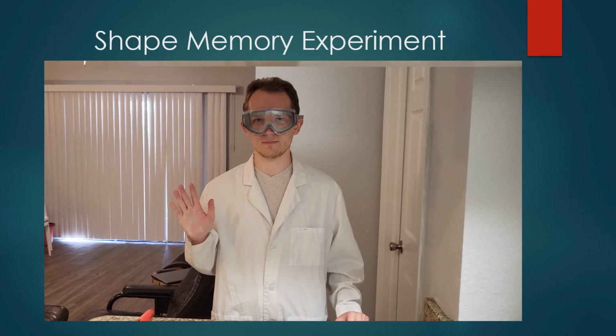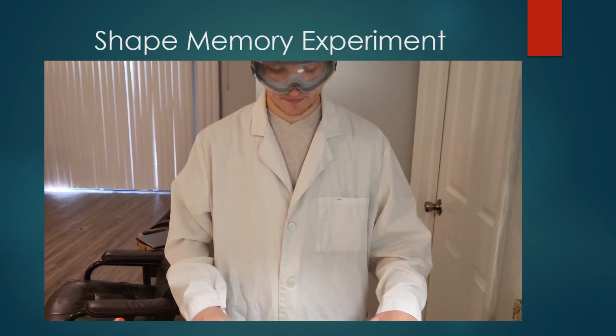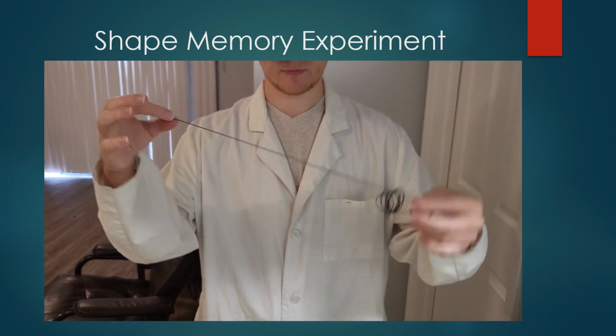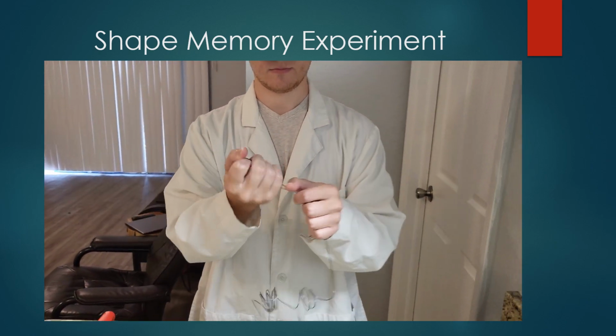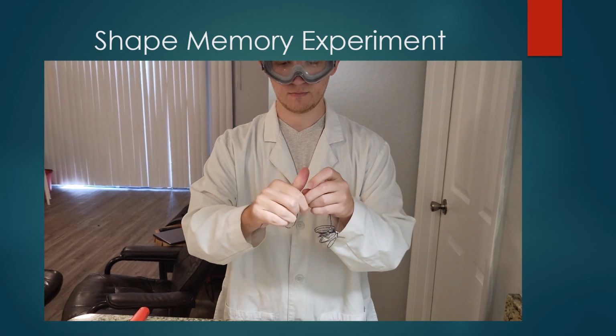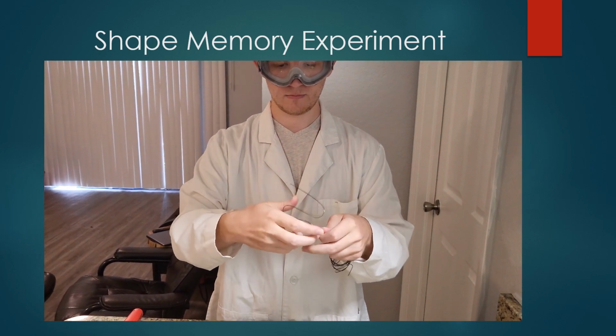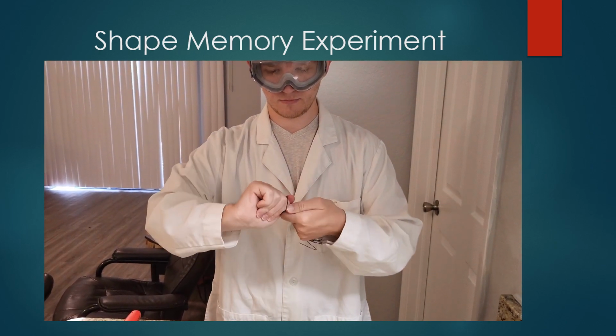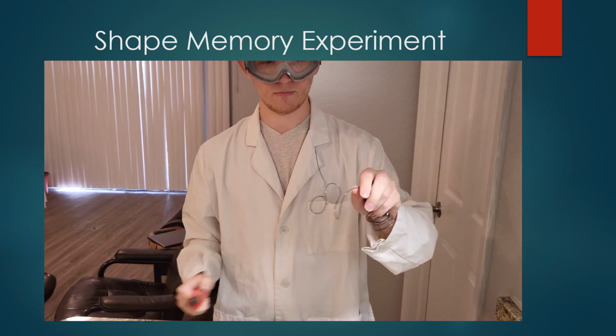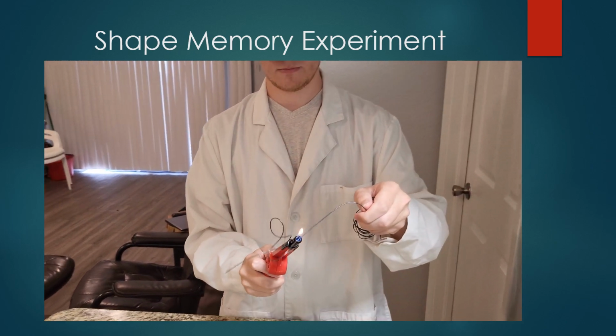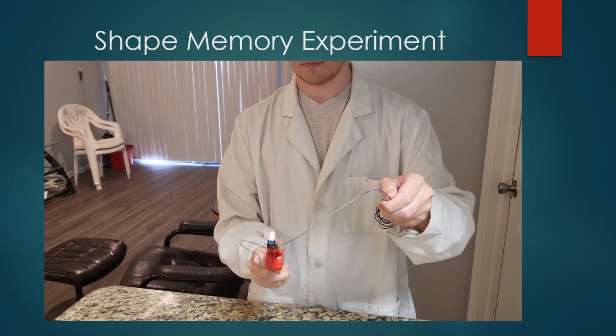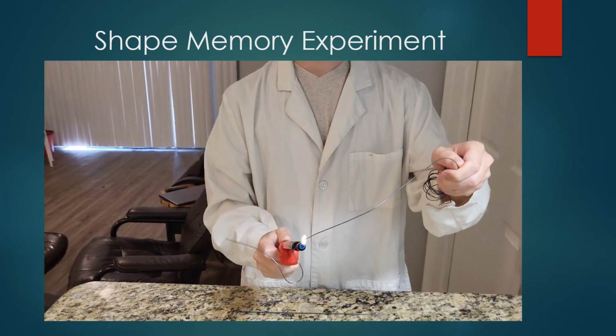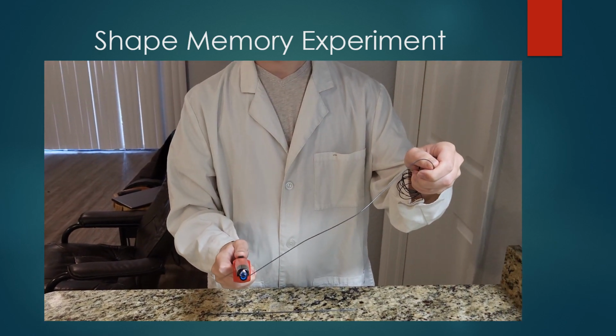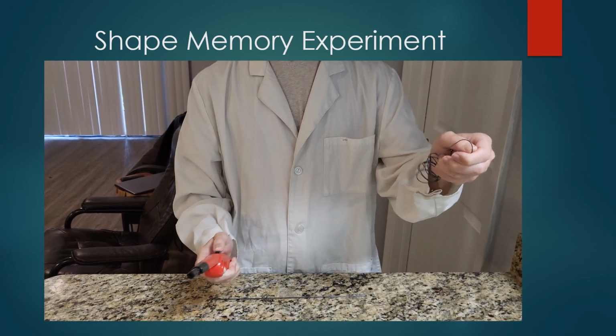The shape memory effect is a reversible crystalline phase transition, and is demonstrated here in our first experiment, where a straight piece of nitinol wire is crumpled up, clearly undergoing plastic deformation. The wire is then heated to a temperature of at least 40 degrees Celsius for this particular wire, and as you can see, it returns to its original straight shape.